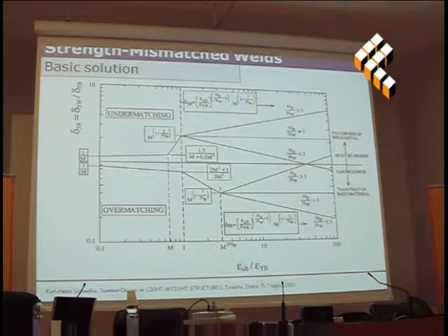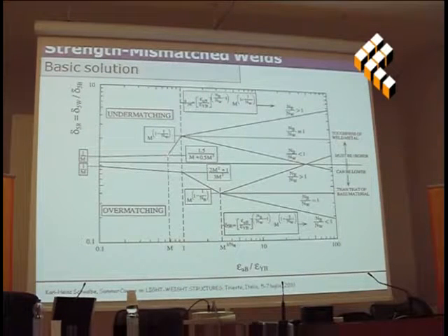And here the base plate, the weld metal becomes plastic. And so the delta 5 has to increase accordingly from here to this point. I can predict this point by this simple equation. And then also the base plate is plastic. So both partners, it's a compound material, a macroscopic compound material. And I think the same principles can be applied to microstructures with mismatch.